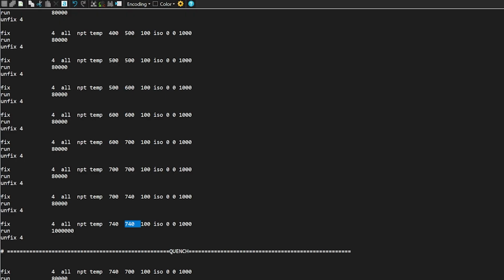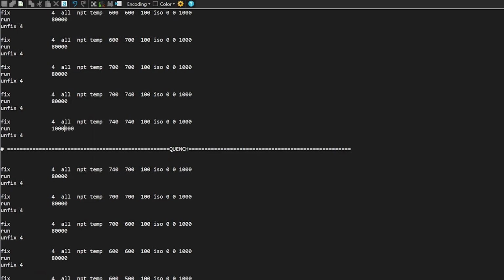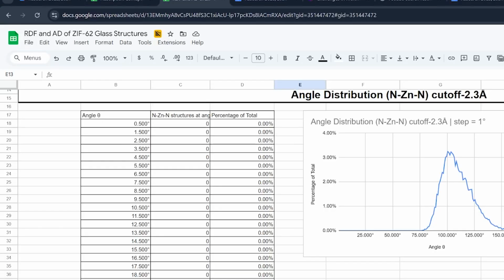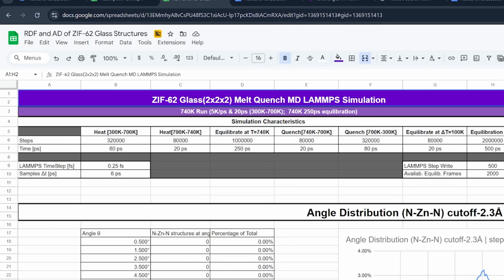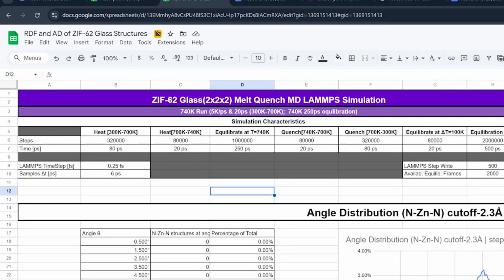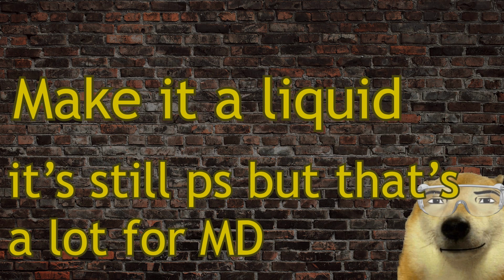The second run, the 740 Kelvin run, tests a key question: does ReaxFF behave better at low temperatures? Instead of going all the way to 1100, the system is only heated slightly above the experimental melting temperatures of ZIF-62. The heating is also slowed down near melting, and the system is held at that temperature for a longer time to allow proper structural rearrangement. This run checks whether a more physically realistic melting process leads to a better glass structure.